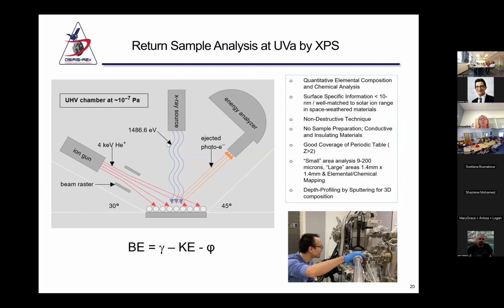So at UVA, we've also been studying the surfaces using a technique called X-ray photoelectron spectroscopy. If you were on the tour two weeks ago or last week, that was my stop. This is a method that uses X-rays to determine the composition and chemistry of the near surface region. The near surface region is about 10 nanometers thick, between 10 and 20 atoms depending on the material. So we're really looking at the surface of these grains.